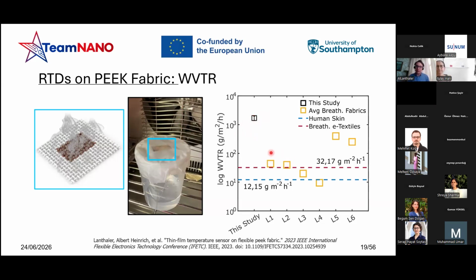And as you can see, comparing the device we fabricated, we were actually able to outscore the majority of the breathable fabrics on the market. Of course, it's a matter of the fabric density of the textile itself, but it's also more breathable compared to the average breathable e-textile found on the market, and also way more breathable than human skin, meaning that the breathability parameter is still preserved.